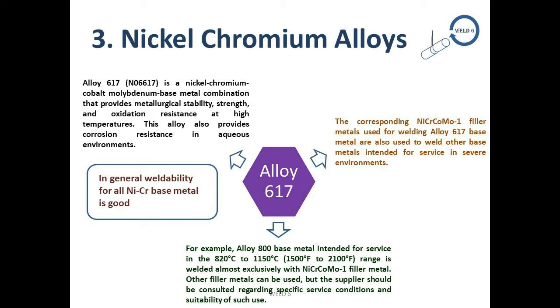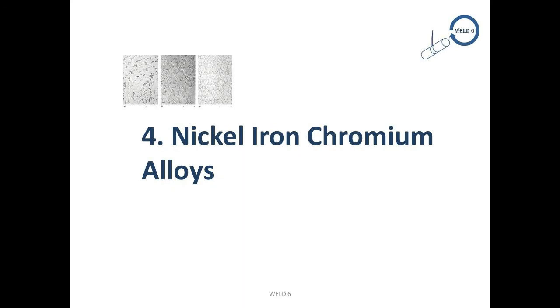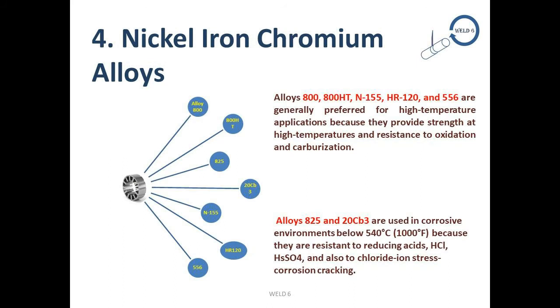In general, weldability is outstanding for all nickel-chromium base metals. The nickel-iron-chromium alloy group includes base metal alloys 800, 800HT, 825, 20Cb3, N155, HR120 and 556. Alloys 800, 800HT, N155, HR120 and 556 are generally preferred for high-temperature applications because they provide strength at high temperatures and resistance to oxidation and carburization. Alloys 825 and 20Cb3 are used in corrosive environments below 540°C because they are resistant to reducing acids — HCl and H2SO4 — and also to chloride ion stress corrosion cracking.